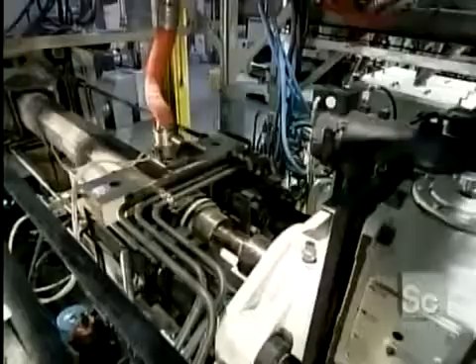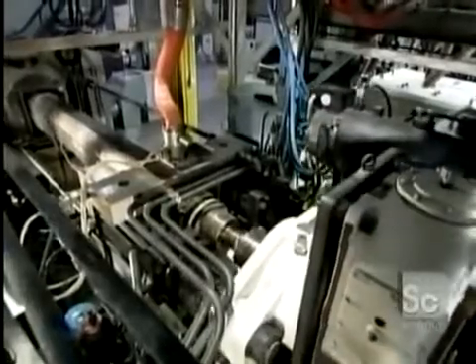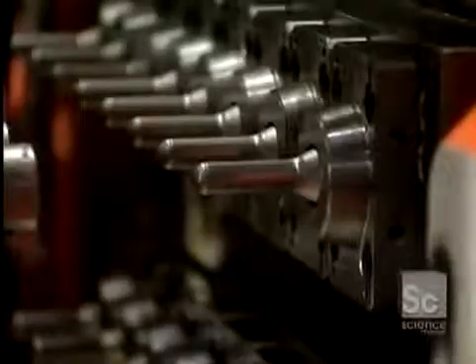The PET drops from the mixer into a plastic injection machine that heats it to a piping 600 degrees Fahrenheit. The dry raw material melts into thick and gooey liquid plastic. The machine then shoots it at high pressure into a mold. This plastic injection molding process casts pieces of plastic called preforms — starter shapes that subsequent machines will transform into bottles or jars.